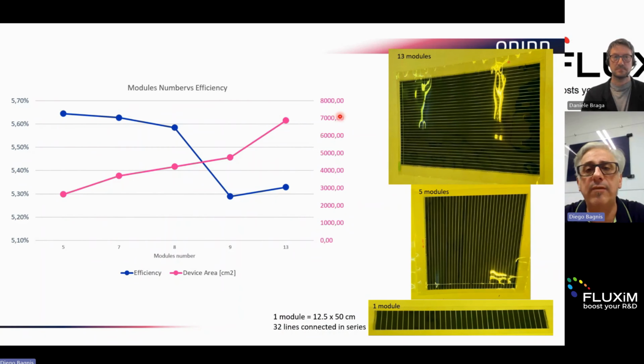and so you see that when you increase the dimension of the active area, it is pretty normal that the performance starts to drop. So in this case, it is clear that depending on the application, and depending on the kind of project for the OPV applied directly, it is possible to choose directly the right panel with the right performance. It is also true that these panels are pretty interesting, because we're speaking about close to 6%, and we are still missing some optimization from our side, for example using the right substrate or whatever.